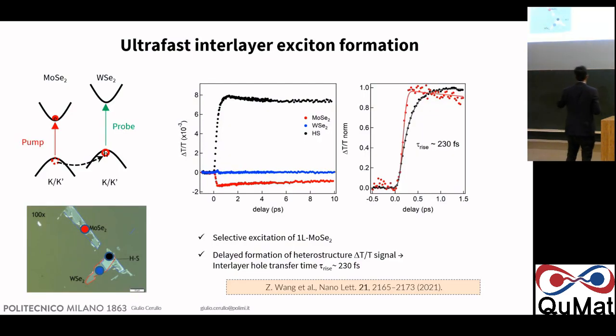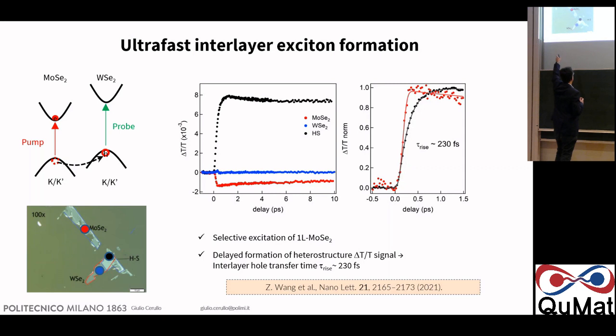Now, the beautiful thing about our sample is that we can really select according to where we put our pump and probe. We can excite the MoSe2, which is the low bandgap, the WSe2, the high bandgap, or the heterostructure. And here we see completely different signals. Now, if we pump the MoSe2 and we probe at the frequency of the WSe2, we see a negative signal. This is due to what is called bandgap renormalization, but it's a rather weak signal that is coming from the monolayer. Now, if we pump the monolayer of WSe2, we are essentially below bandgap, so we see zero signal. And this is again what we expect.